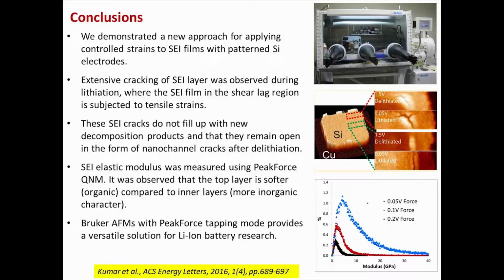Also, we used PFQNM to measure the elastic modulus values and could verify that the top layer is softer compared to the inner layers, which have more inorganic character. And lastly, Bruker AFMs with peak force tapping mode provide a versatile solution for lithium-ion battery research. Most of the results I have presented today have already been published in this paper, which is at the